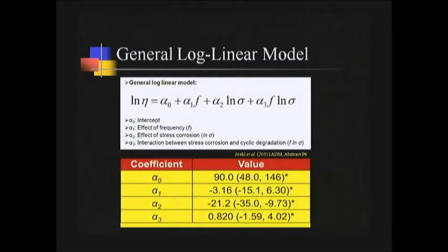But just briefly, what we see when we apply the general log linear model is that he has looked at the Emax Zirpress material, and he saw when looking at the coefficient for the first term that its 95% confidence interval overlaps 0, and the first term is frequency. So he is not seeing a frequency effect with that material.